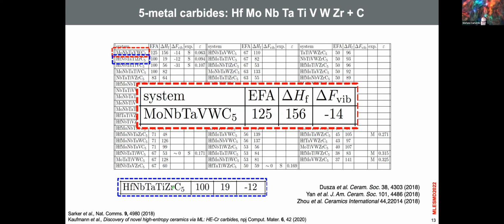So if you are mixing rock salt powder, what do you expect? I'm going to have a rock salt entropy stabilized system, or high entropy system. That's exactly what they did, because the outcome is rock salt. So pretty much by understanding that the precursors were rock salt, an experimentalist can infer and say, well, okay, this might be a good test system, and it's going to show up. Effectively, it does show up. Very little loss in enthalpy.